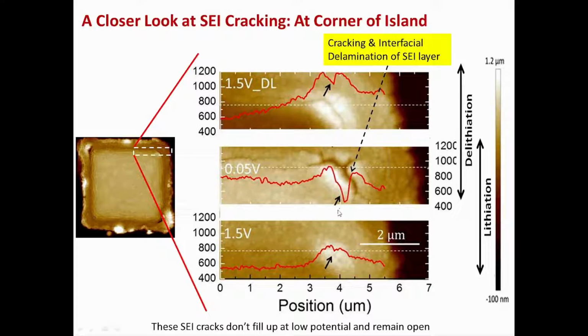There might be a possibility that the cracks only fill at the bottom, which is very hard to see because of some of the problems associated with the tip geometry and how far it can reach in the crack. But given all that, the cracks don't completely close up. And you see the white region surrounding these cracks, which just tells us that the height is higher there, which means there is a partial delamination happening at the silicon and SEI interface. So there is cracking of the SEI layer, and as it cracks, partial delamination also results.